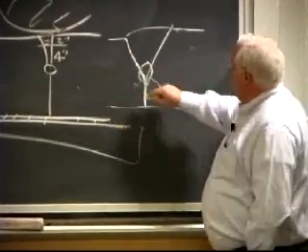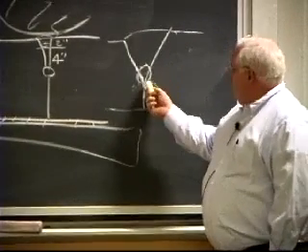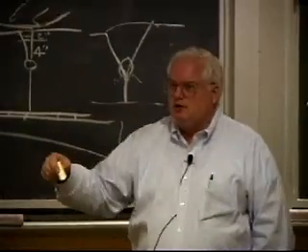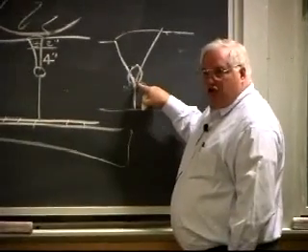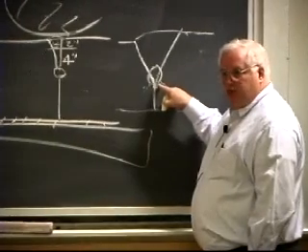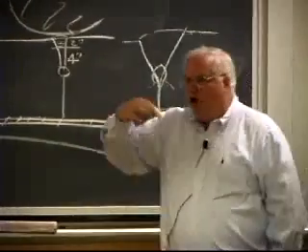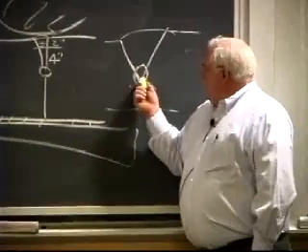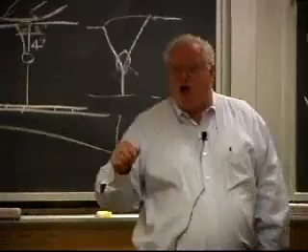If I wanted to get a full penetration weld, and I'm going to weld from the bottom side on a heavy plate, I'll have to go back in and gouge it out. I can do it by grinding to take out the lack of fusion defects that are there, where the metal didn't melt together properly, kind of overlapped cold and solidified against it without a weld. I either have to grind it out or I have to air arc gouge it out.